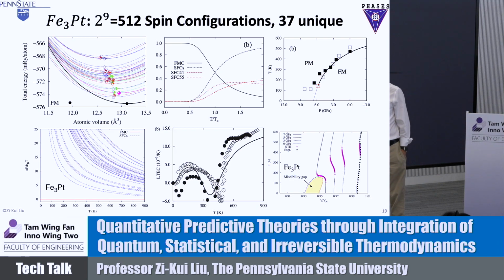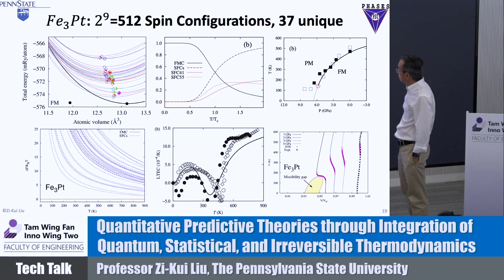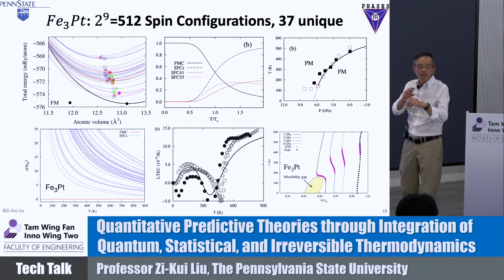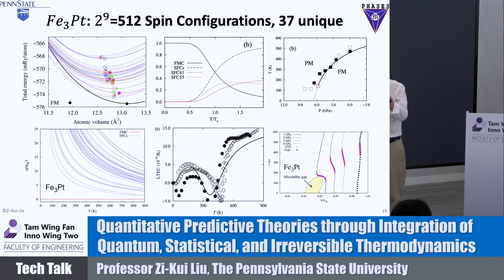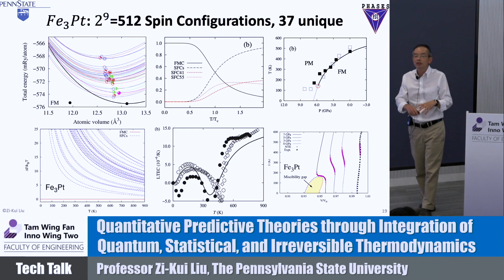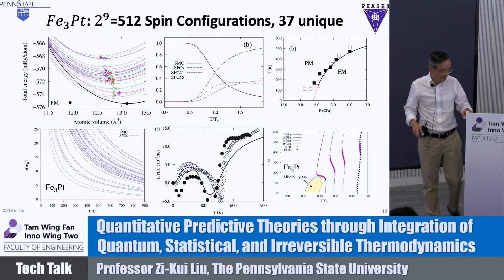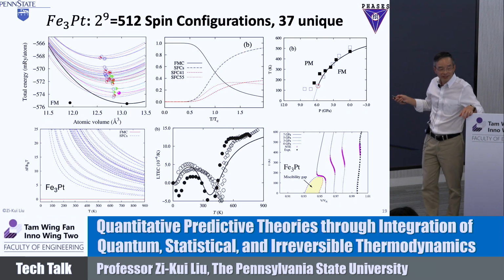It's actually now a new experiment by Brookhaven National Lab. They measure local bonding. There's no soft modes. And the local bonding does not decrease as temperature goes up. As temperature goes up, the local bonding always increases. So the only reason you have negative thermal expansion is because when the temperature goes up, the population of the smaller volume one increases. Each of them has some expansion, but total volume could decrease because the smaller volume ones replace the bigger volume one. So total volume decreases. So there are no soft modes based on this classical theory. We hope we can convince people on that.